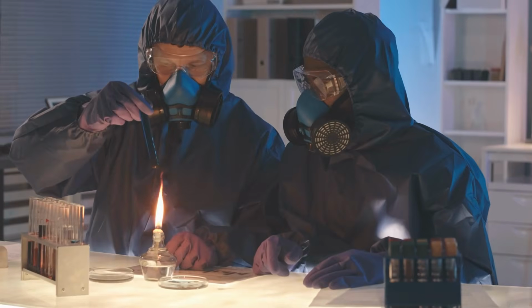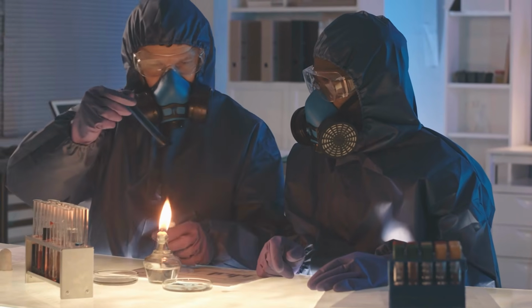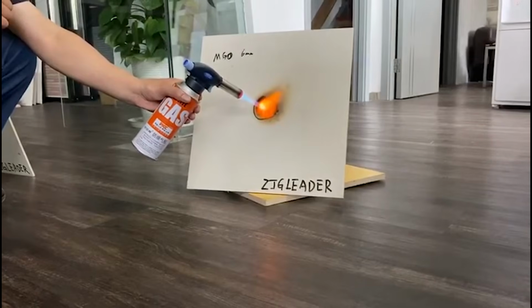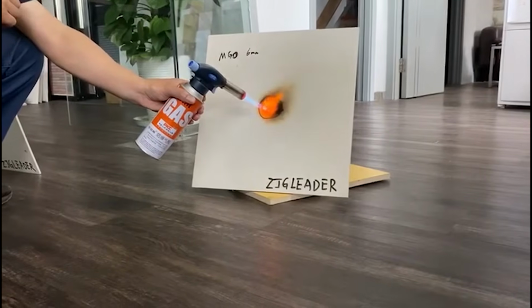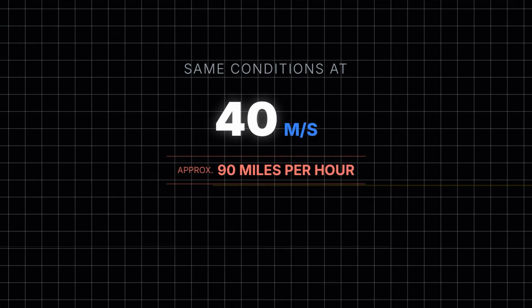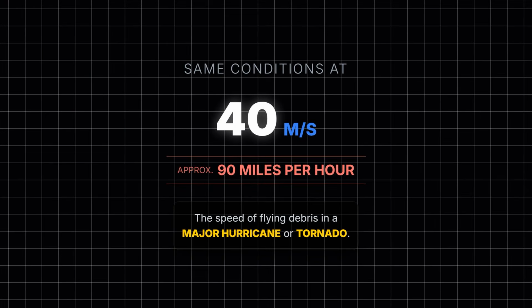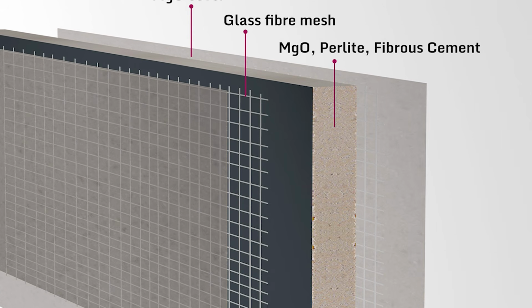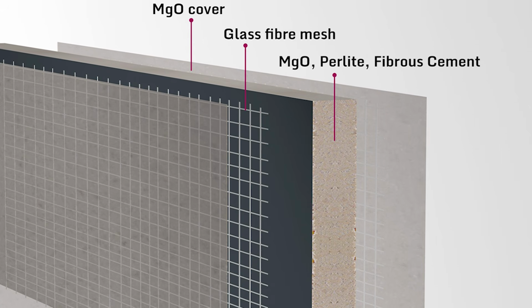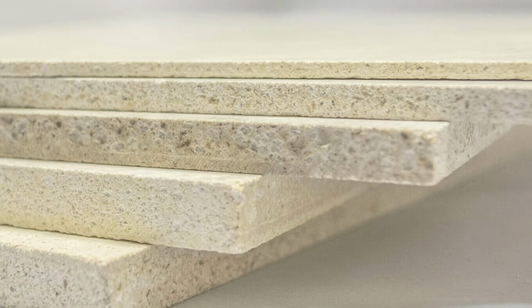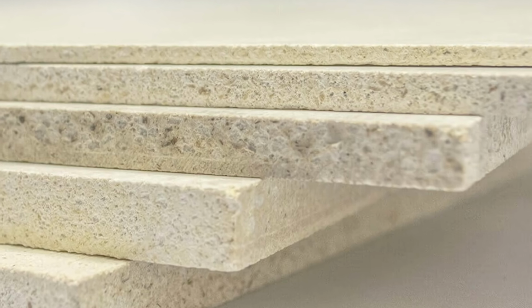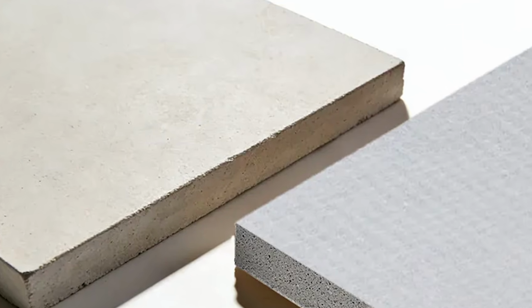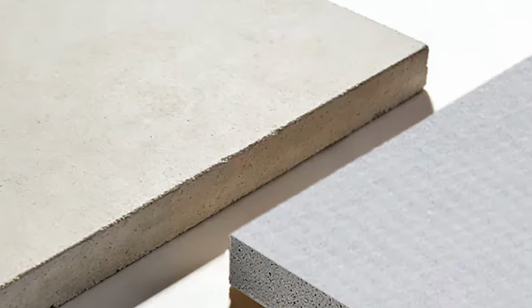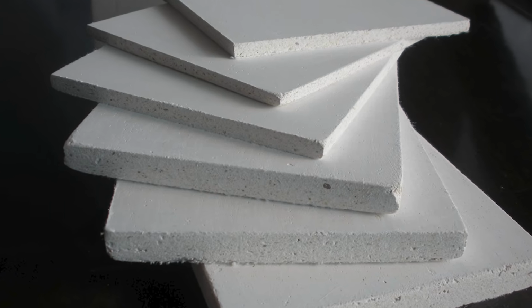At Curtin University in Perth, Australia, researchers Wu Chen and Hong Hao spent 4 years firing 2x4 timber boards from pneumatic cannon systems at wall panels at 40 meters per second, approximately 90 miles per hour, the speed of debris in a major hurricane or tornado. OSB-skinned structural insulated panels, the standard product, suffered what the researchers described as localized punching shear failure. The board passed through the wall. MgO panels reinforced with glass fibre mesh stopped penetration entirely.